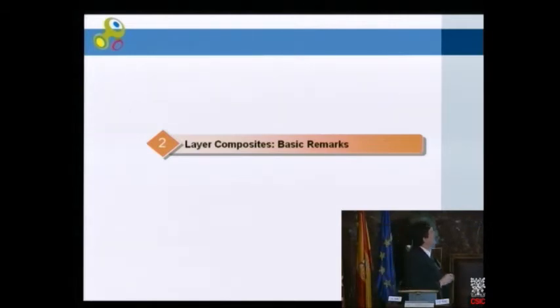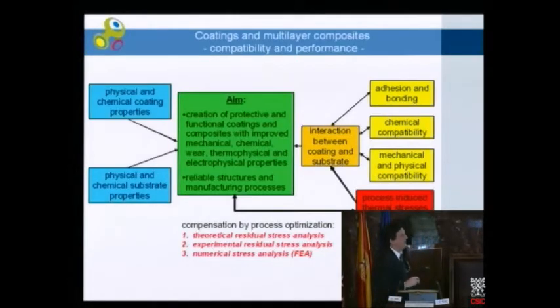Coatings understood as layer composites. What does it mean? It first means a completely different theoretical approach. Just to combine one material with the other, that is the traditional way, but this cannot be the standard we follow in these years. That means the creation of protective and functional coatings and to combine them with the properties of the structural material as a carrier, this is well known and well understood. But we finally need a reliable structure, and we also need a reliable manufacturing process. And this gives you the first smell that just to combine the two materials by far is not enough.